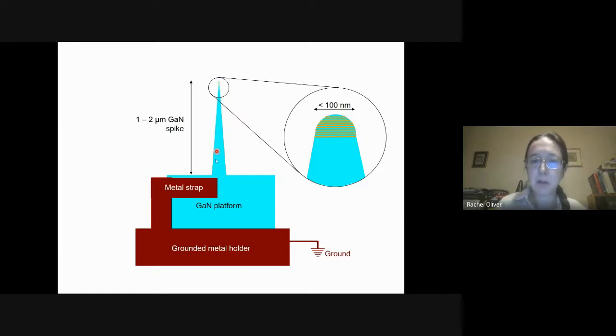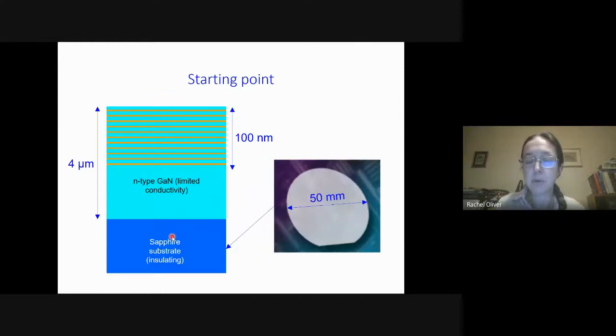It needed to be on the end of a long spike, so about 100 nanometers at the apex, but about 2 microns high. And then it needed to be attached to our voltage source and with reasonable conductivity, all kind of connected together. And we had to figure out how to make that. And our starting point is a long way from being a needle. It's a flat sapphire wafer with a layer of N-type gallium nitride on top and the quantum wells above that, which, far from being a 100 nanometer apex, typical wafer is 50 millimeters or 2 inches across.